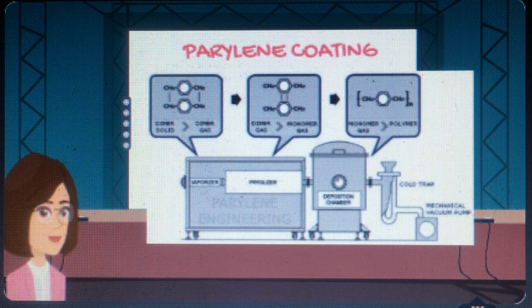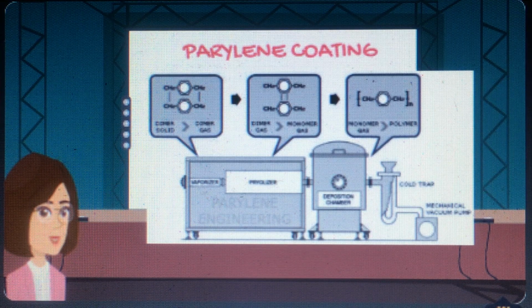Process of parylene. Parylenes are formed at around 0.1 torr. Under these conditions, the mean free path of the gas molecules in the deposition chamber is on the order of 0.1 centimeters. Therefore, the deposition is not line of sight, and all sides of an object to be encapsulated are uniformly impinged by the gaseous monomer. This is responsible for the truly conformal nature of the coating. The process consists of three distinct steps as shown.